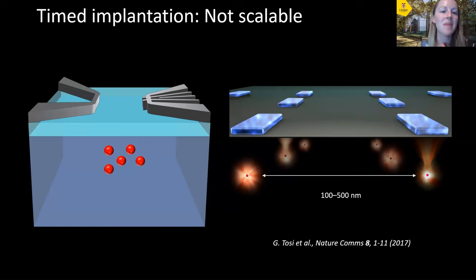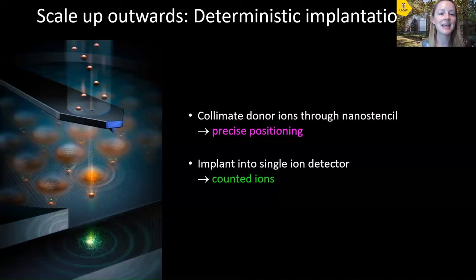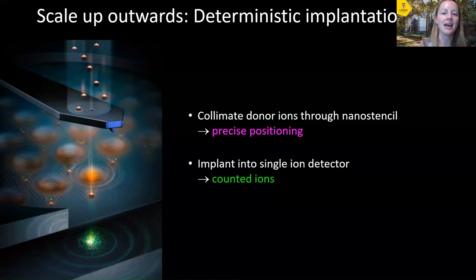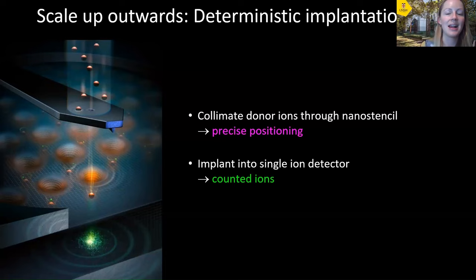So how can we make these arrays of qubits? So we're looking into scaling up outwards by pursuing something called deterministic single ion implantation. And with this method, we would collimate our donor ions through a movable atomic force microscope nanostencil that allows us to precisely place our donors in silicon. And then by implanting these single ions into a single ion detector, we can effectively count in an exact number of ions and create arrays of donors in a step and repeat fashion.